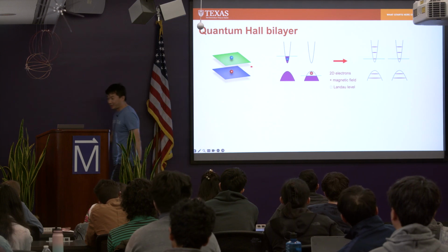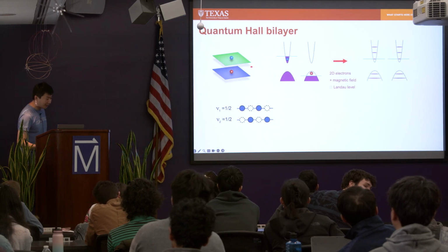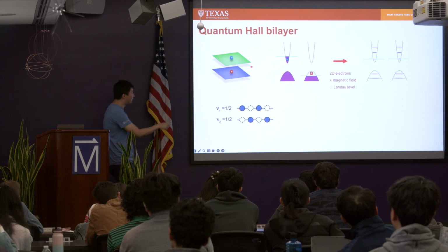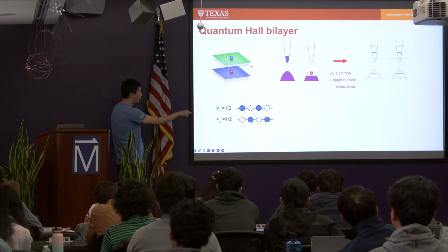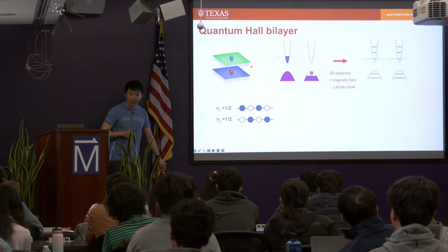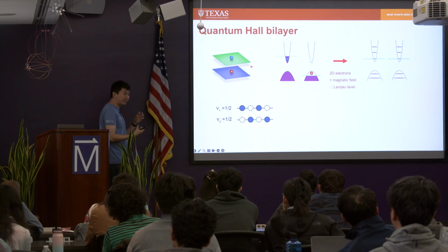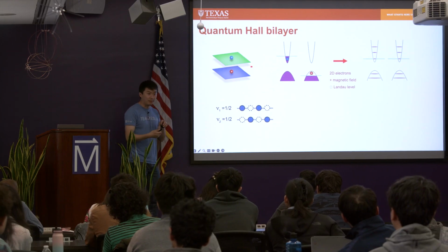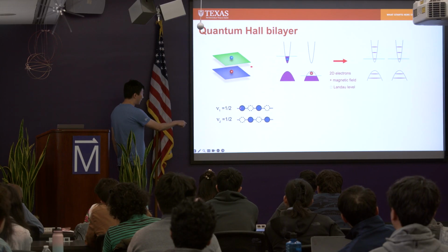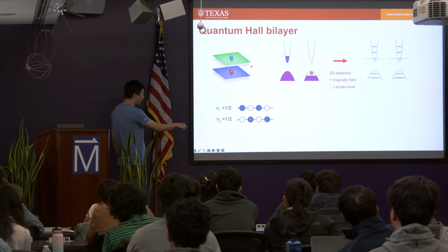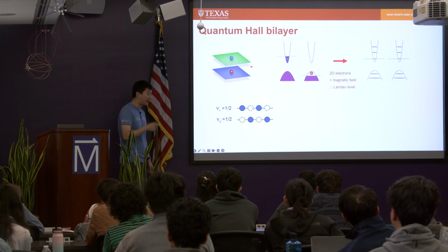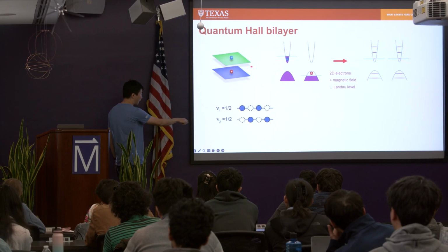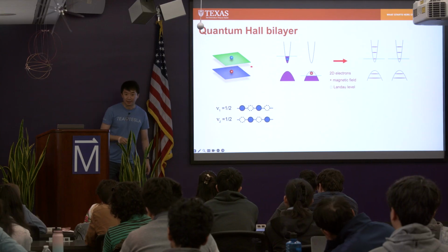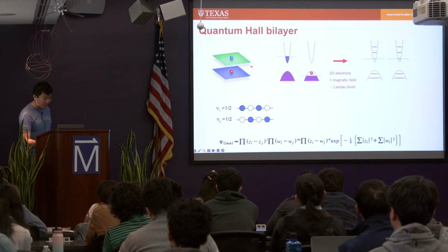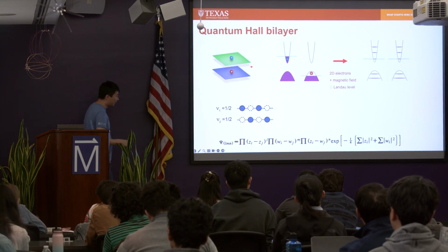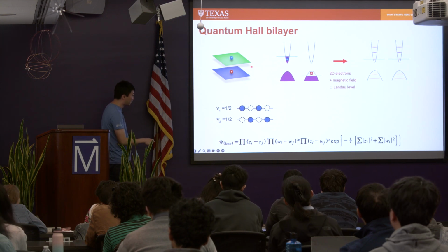So in this situation, all we need to do is to put one layer at 1/2 filling, the other layer also at 1/2 filling, right? And if there's very strong interlayer coupling, then the electron on one layer will misalign with the electron on the other layer, right? In other words, that electron here is always aligned with the hole in the other layer, right?